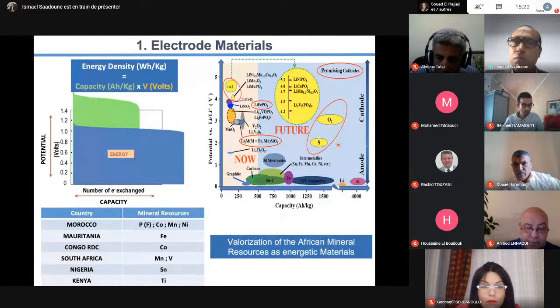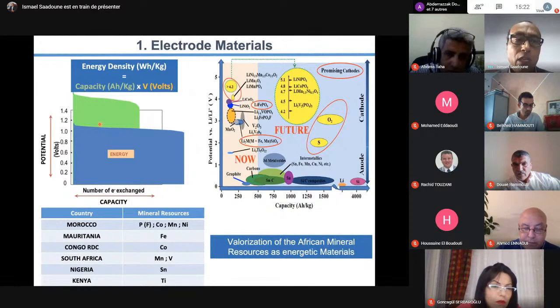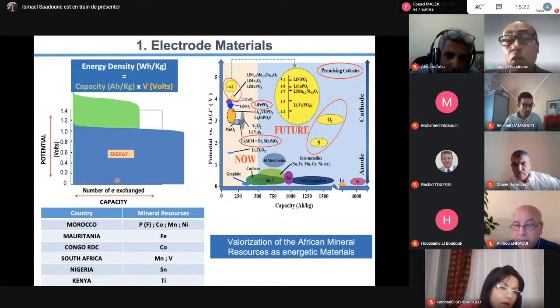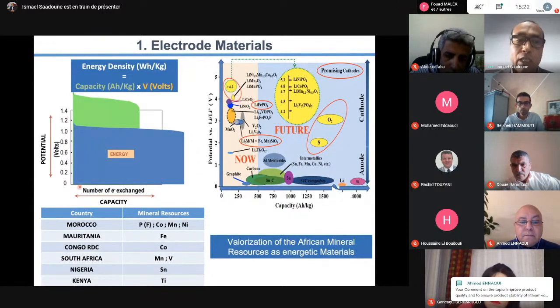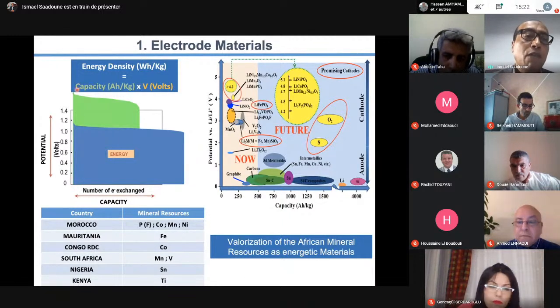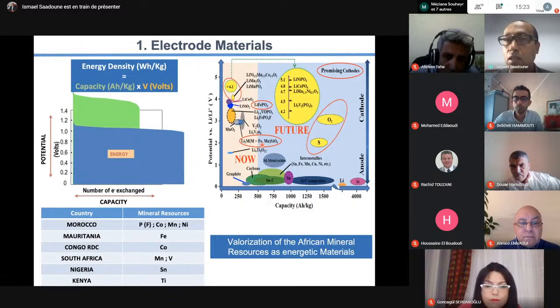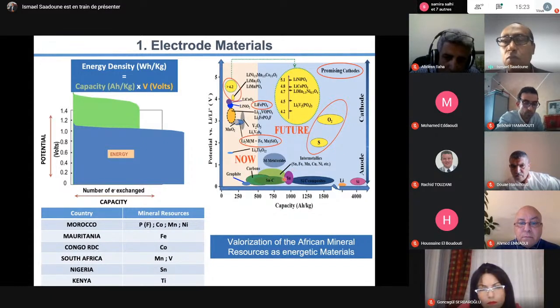So if we look at the calculation, what does having high energy density mean? High energy density is the capacity multiplied by the voltage. So if you would like to have a big energy storage capacity, you should have a big number of exchanged lithium. You remember, this gives you the capacity, or having a high voltage. If you have these two approaches in mind, and see what exists in the literature, we have some low voltage materials like tin, carbon, graphite, and so on. They have low voltage, so they are good materials with high capacity. You see here, they are good materials for the anode side.